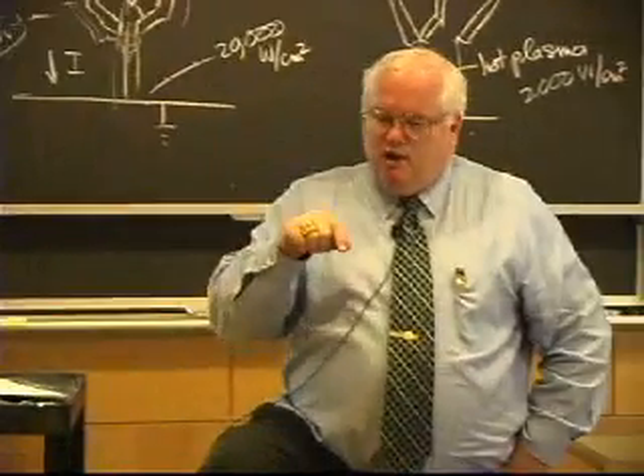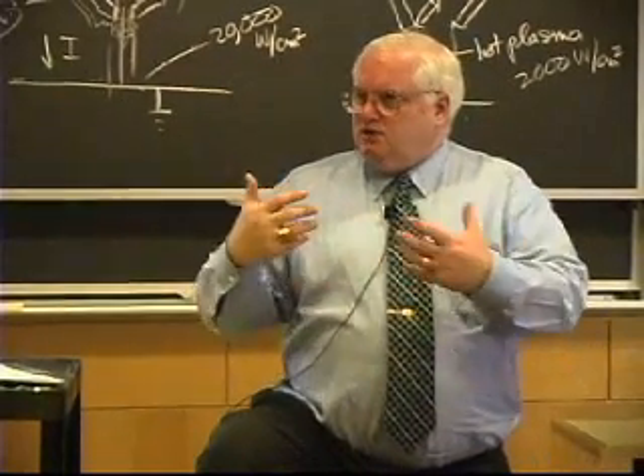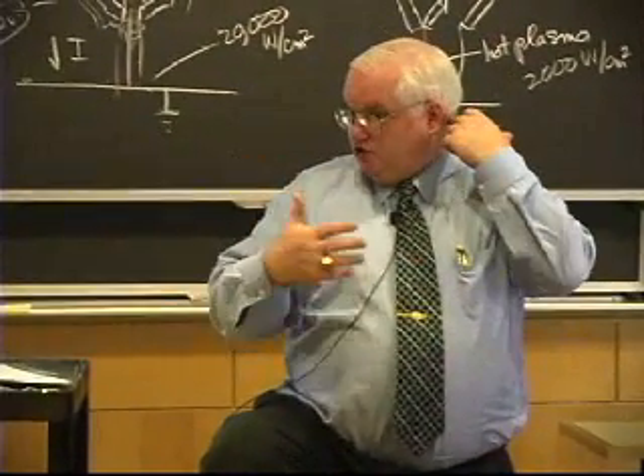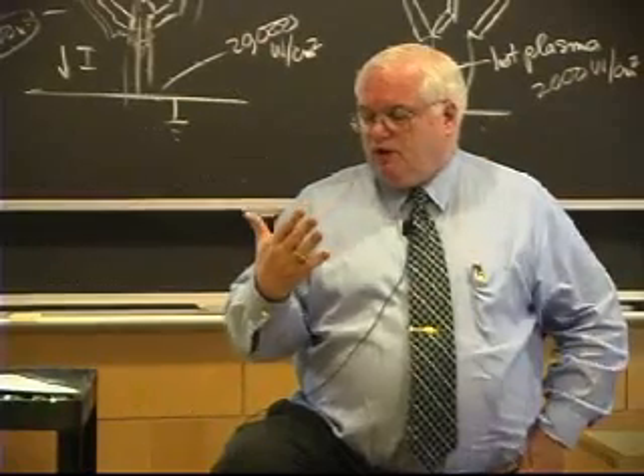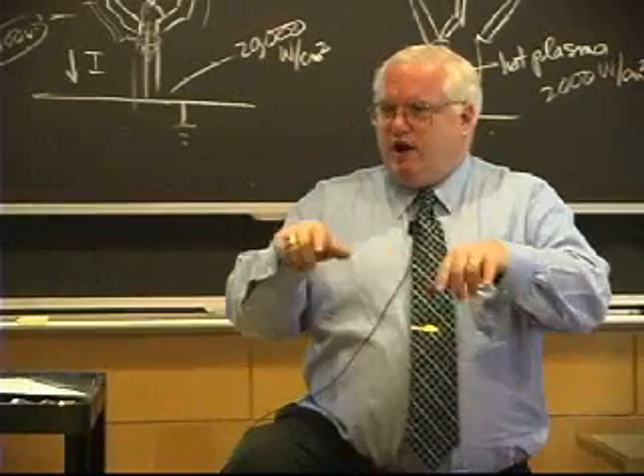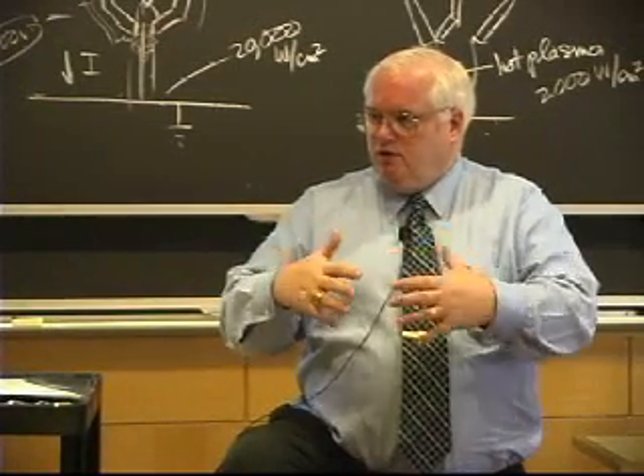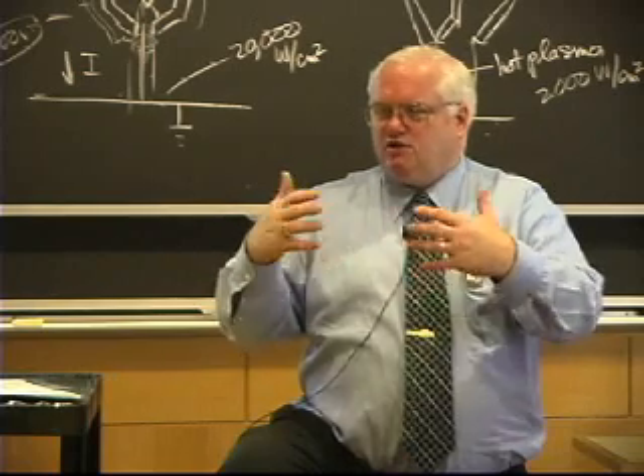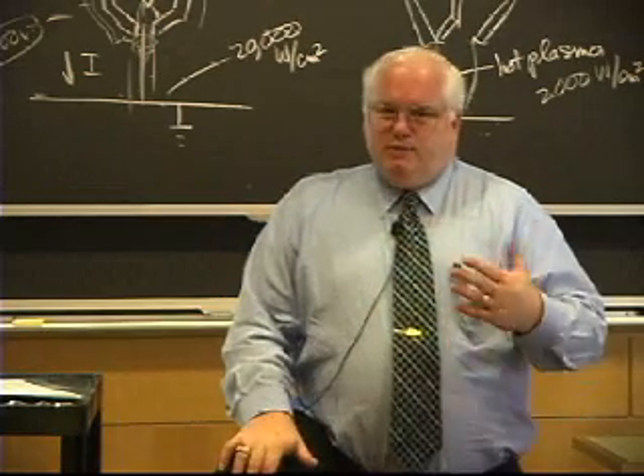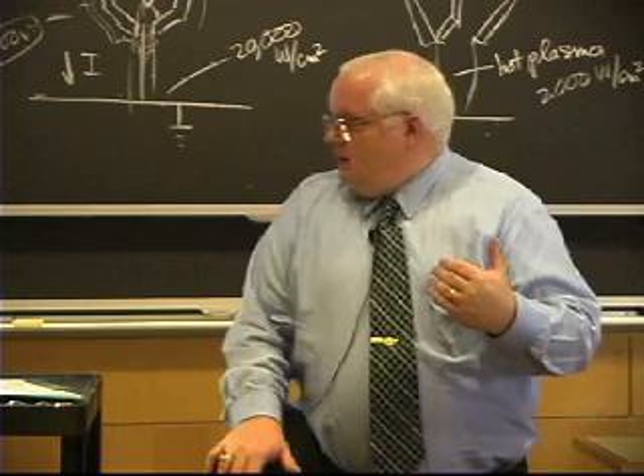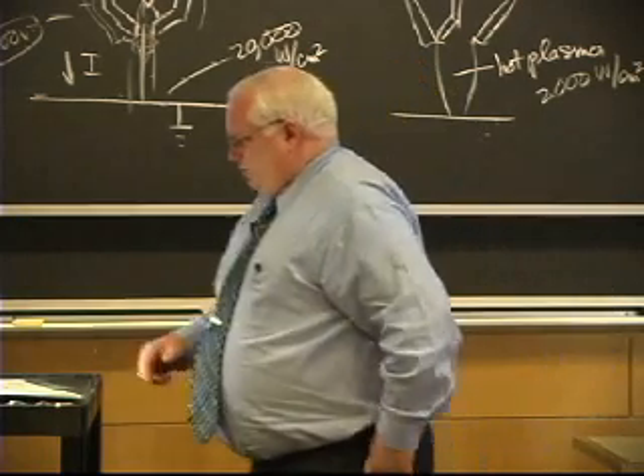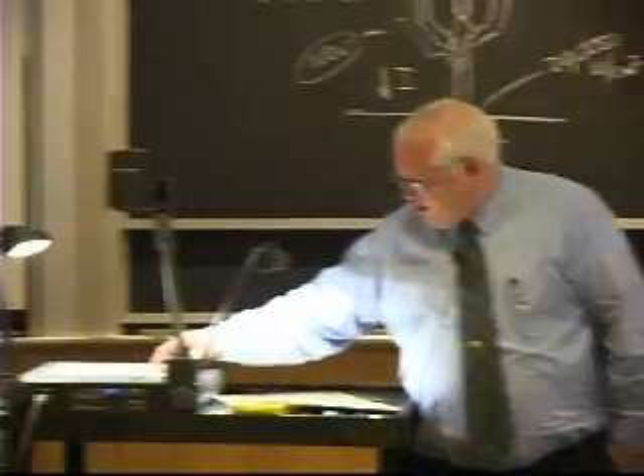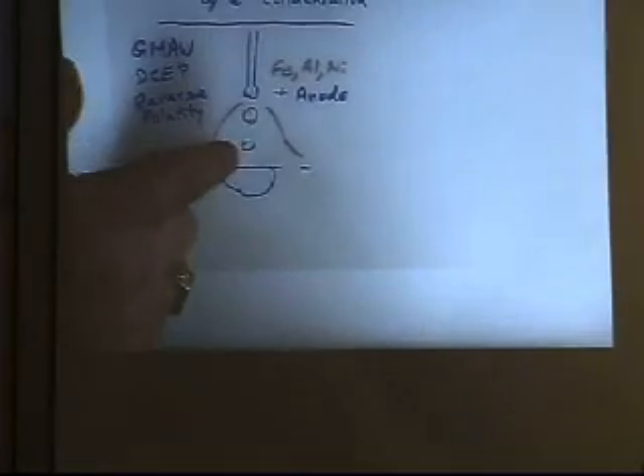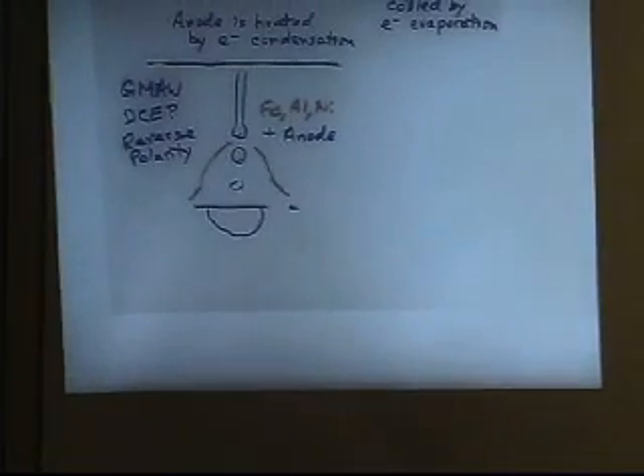But you actually can see, if you change the polarity, how you break up the oxide surrounding the weld. If you watch it through the lens while it's welding, you can see surrounding the outside of the weld as you're moving along the oxide being cleaned off. Now most people, if you go to the welding handbook, will tell you that's because when you change the polarity, all those positive argon ions are going to be impacted against the surface and break up that oxide. Well, that's not true.